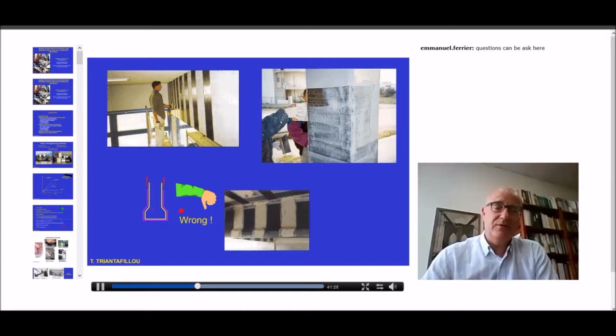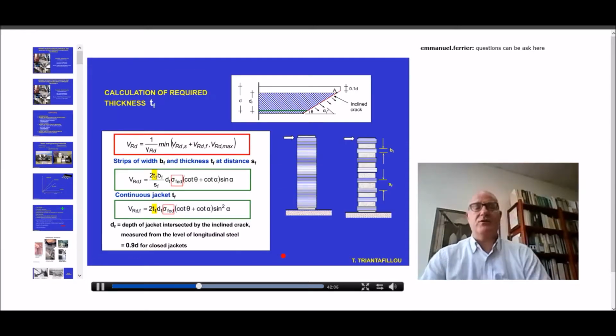This is wrong because if you think that tension is applied to the jacket, if the jacket is activated to carry shear forces, it will have to carry tension, and this tension will result in local debonding here in those reentrant corners due to a resultant force that goes outwards. In that case, one should apply perhaps some kind of local anchorage. So let's try to be careful when it comes to the practical execution.